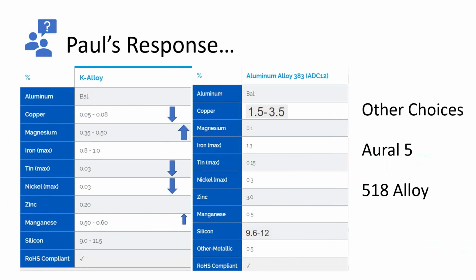Here we're now looking at the chemistry, a direct comparison of K alloy on the left and aluminum 383 or ADC 12 on the right. We can see that the copper is probably the single biggest difference. The K alloy has extremely low copper, and I've made this a little bit larger so we can see the copper levels of ADC 12. There are several different specs. Customers have specs on ADC 12, and some customers tighten this range, but overall it's going to fall somewhere within 1.5 to 3.5% copper.